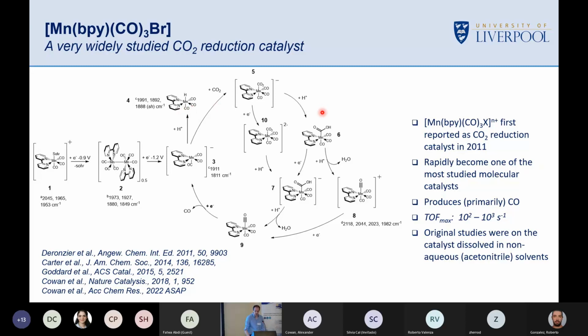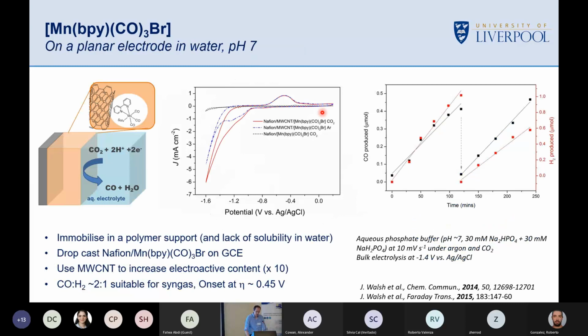With stronger acids, we get higher CO2 turnover. We thought, well, this could be interesting. Let's give this a shot. So it was developed originally to work in non-aqueous solvents, but you can just very simply deposit the catalyst onto a carbon support. This is a planar electrode, and we put some carbon nanotubes in just to get the surface area up. And I'm not going to go through this in great detail, but say the reds with carbon dioxide present, the blues under argon, and you can see quite a large current enhancement.